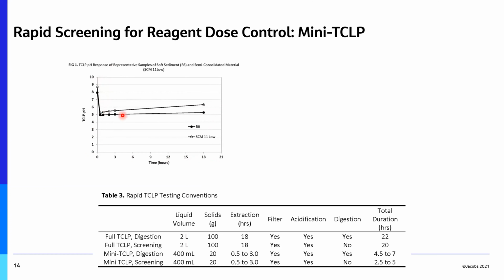And what we found was, for the soft dredge material and the semi-consolidated material, in an hour, with the soft dredge material, I had virtually the same pH that I would if I ran that test for 18 hours. Well, that really condenses my time frame and allows real-time processing. The same thing happened on the SCM low. In fact, the numbers ended up being conservative on both of those. So that seemed to be the way out of the woods.